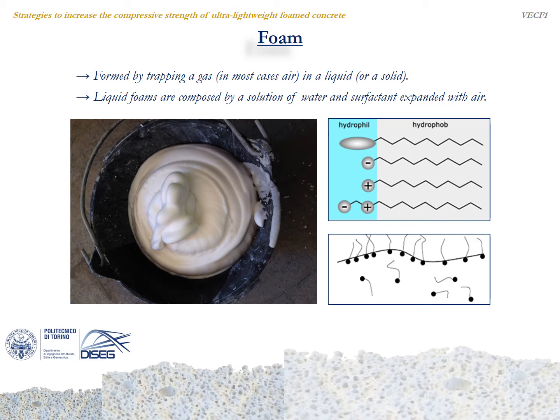Liquid foams are composed of a solution of water and surfactant expanded with air. Surfactant molecules, which are amphiphilic, prefer to be present at the air-fluid interface, and they arrange themselves so that the tail groups are in contact with the air, while keeping the head groups within the liquid. They play the fundamental role of increasing the lifetime of the foam.